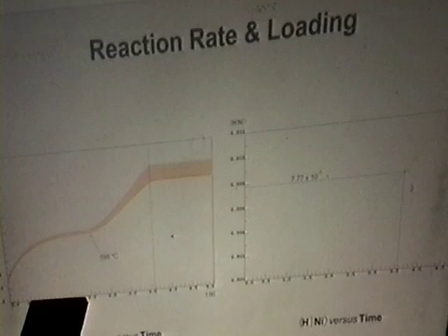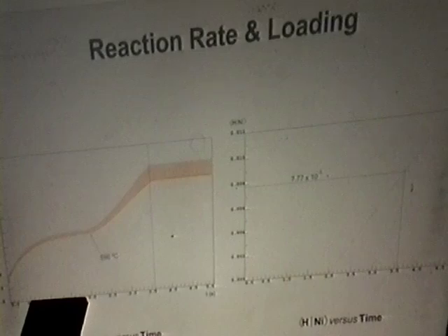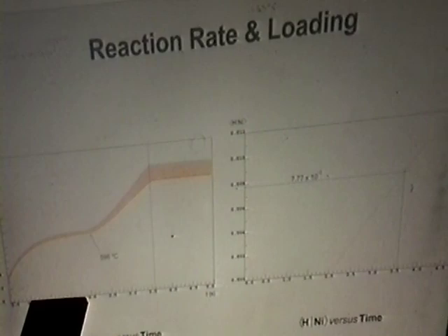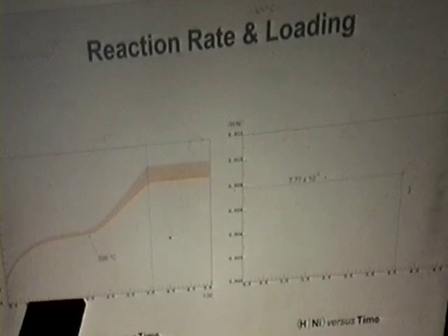So we reduce a lot the time scale. Otherwise, the simulator goes on for days. So we put seconds instead of minutes, because if we imagine that some hydrogen coming from the solid source goes into the nickel, we can have the hydrogen concentration rising up, we imagine linearly, just to simplify the simulation. And if we look at the curve of the temperature of the sample, we can see that from the steady state temperature, something close to 600 degrees, we rise up to the melting temperature of the nickel layer very fast.